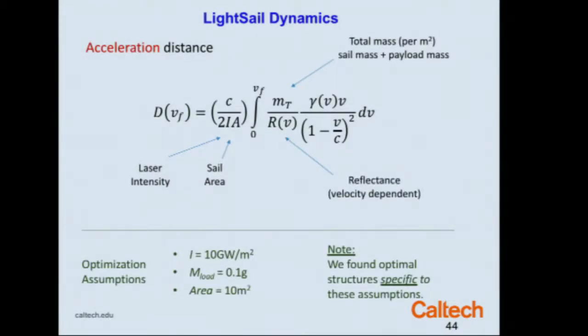So the acceleration distance is now related to the speed of light, the area of the sail, the reflectivity, this relativistic correction, velocity, and so forth. And so I can compute this distance that I need to, so for those structures that I showed you, we permuted over and made a little more than 100,000 different simulations.